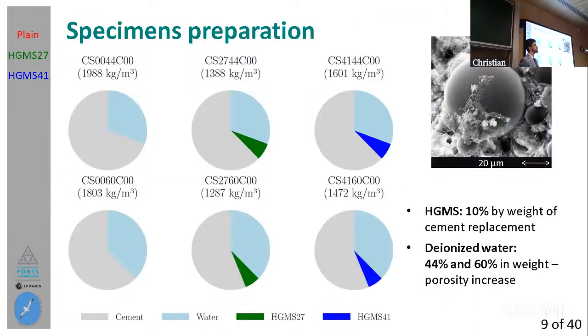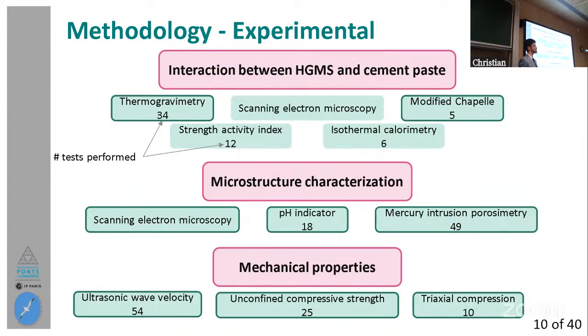Okay. So you make the MIP test for the size distribution, for the microstructure characterization. Yes. And you do not do a diffusivity test or a permeability test. Why? They are found to be very important parameters. And why mercury intrusion porosimetry? Why not, for example, a nitrogen adsorption test or water absorption test that can indirectly as well give some kind of pore size distribution, and which I think are less aggressive.